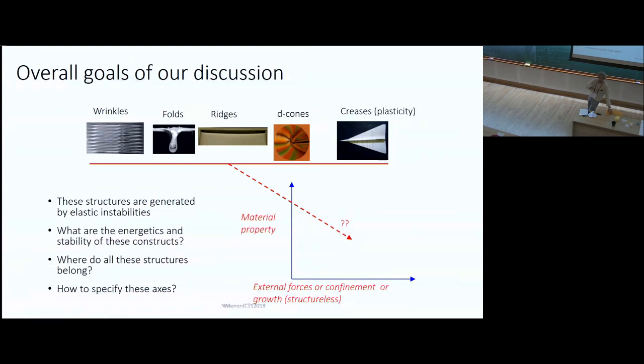Graphene and other truly molecularly thin materials, we are close to molecularly thin sometimes when you go to 10 nanometers, but this is not single molecule by any means. This is really continuum. But those materials, the first relation I told you is in continuum, bending goes as E times thickness cubed, stretching goes as E times thickness. That's not true for a graphene sheet. The physics of stretching those rings is quite different from the physics of bending them. You can't integrate over the height of this thing and get an answer out. So these things are two independent numbers.